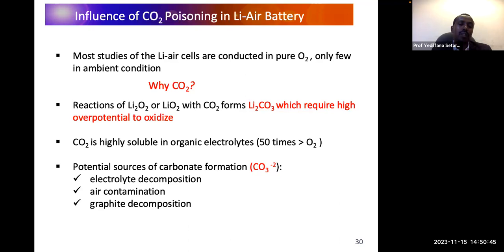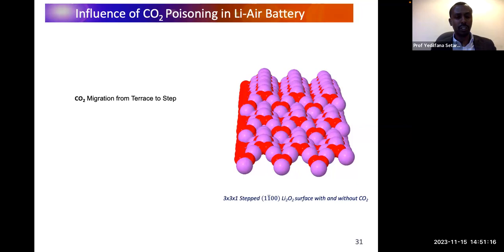The third possible scenario is graphite can decompose. We have porous carbon that supports the growth of the lithium oxide at the cathode site. So this graphite may decompose, and the decomposition product would be carbonate. So there are possibilities of having a carbonate, so we need to consider how the growth mechanism is taking place in the presence of carbon dioxide that results in carbonate formation.